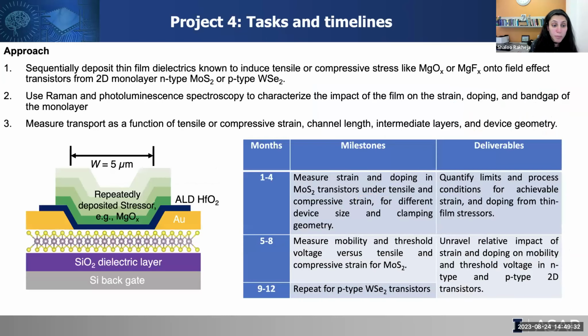So in terms of the approach, the figure at the bottom shows what they're going to be able to do. They are going to sequentially deposit these thin film dielectrics, which can induce tensile or compressive stress onto these field effect transistors. And they are going to target molybdenum sulfide and tungsten selenide to begin with in this particular year. They actually have developed a method for extracting local strain and doping using Raman. And they also have models that can explain how strain is transferred into the 2D material.